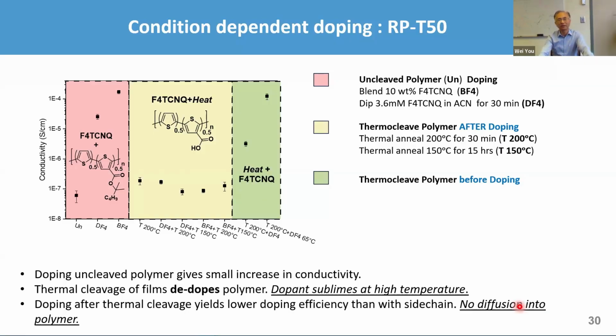So now if you look in here, it's interesting, right? This conductivity is 10 to the negative 7, which is essentially insulating. If you put F4TCNQ to work with this material, you will increase the conductivity by 10 to the third, which is very good. But still, we're talking about 10 to the negative 4 conductivity, which is very low. So depending on the doping method, either you dip them or you blend them, you can get slightly higher conductivity, but it's still very low though.